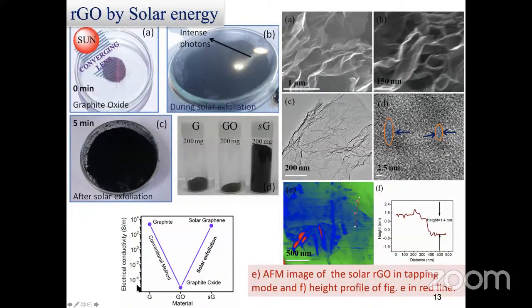The most interesting thing is the electrical conductivity. Graphite has excellent electrical conductivity, almost 10 to the power of 3 Siemens per meter. But this graphite oxide has a very low electrical conductivity, almost 7 orders less, 10 to the power of minus 4 Siemens per meter. So this material cannot be used for any of these electrical applications, for example solar cell, supercapacitor, fuel cells, batteries.